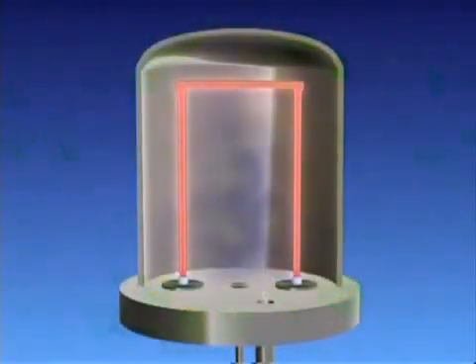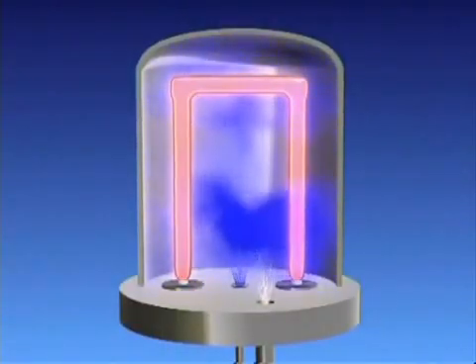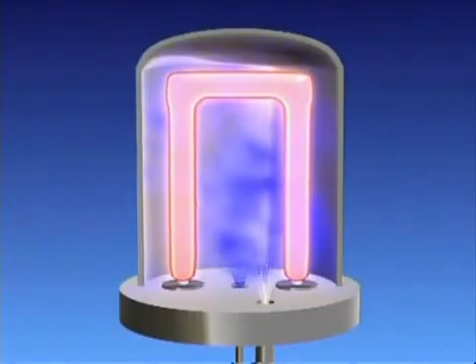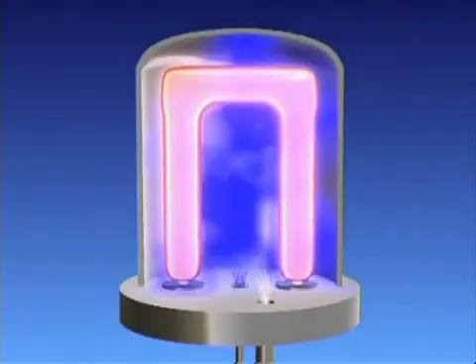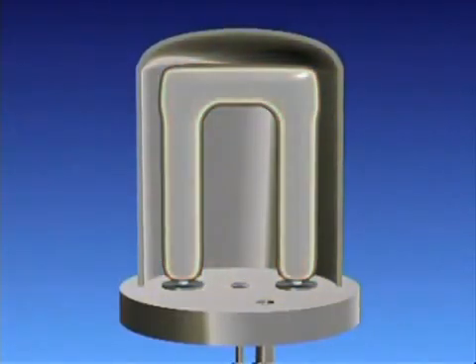After extensive distillation steps, the now hyper-pure trichlorosilane is reduced by hydrogen at around 1,100 degrees centigrade to form silicon again, which is deposited on electrically heated hyper-pure silicon rods. Hyper-pure elemental silicon grows on the rods in polycrystalline form until an ingot of specified diameter is obtained. This process takes roughly one week.